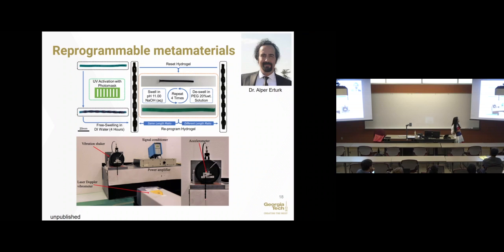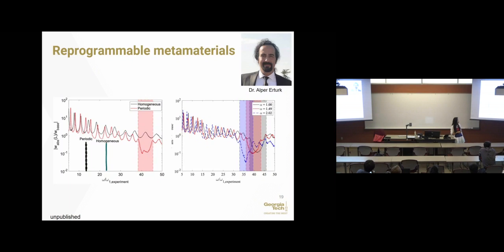And then in collaboration with my colleague, Alper Erturk, we are trying to use this property of the material for some applications. The simplest one that we tried is, well, now we have this gel beam, right? We can shine light on it and generate this periodic structure. You can't do this using the previous light-sensitive gel, because after you remove the light, it will come back to the original shape. But now we can keep this shape. My colleague took the sample, shook it from the top and measured the vibration from the bottom. We wanted to see whether this periodic structure can give us some interesting wave or vibration propagation property.